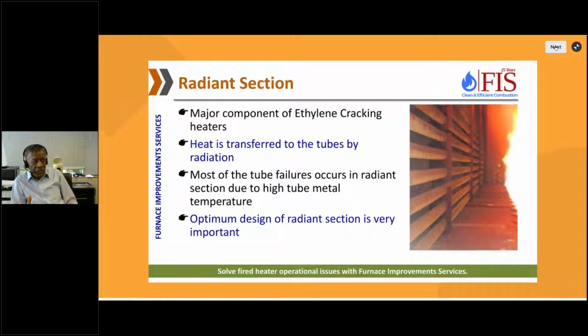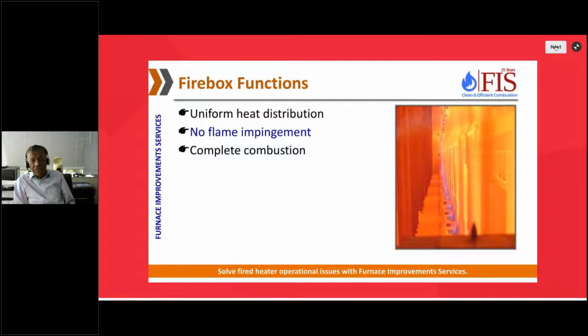So in the radiant section, that's where heat transfer by radiation is taking place. Almost 80 to 90% of the heat transfer which takes place in the radiant section is by radiation. Say about 10% is by convection. Also, most of the tube failures which occur in cracking furnaces are in the radiant section due to high tube metal temperature, carburization, and all those types of things. So we feel optimum design of the radiant section is very, very important. So we'll talk about the radiant section.